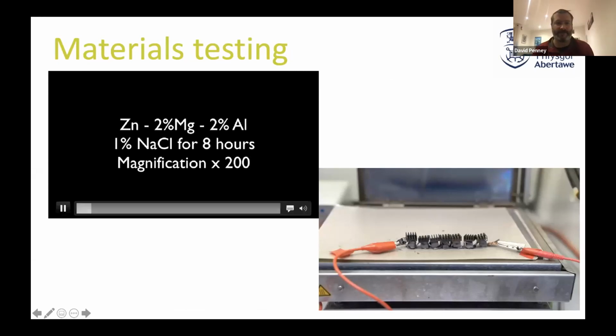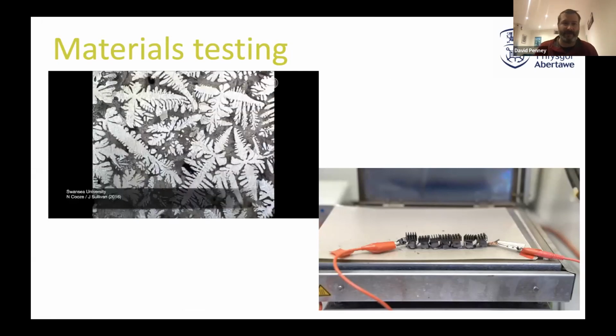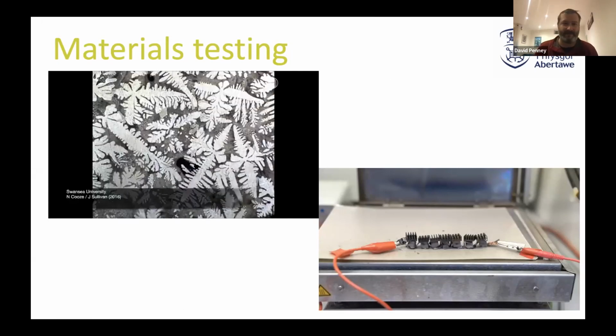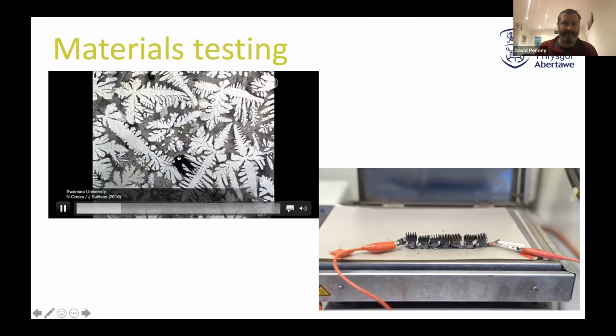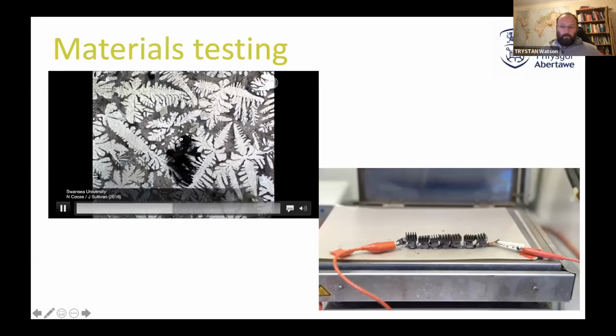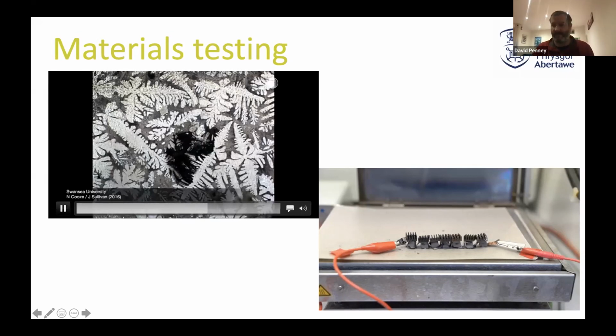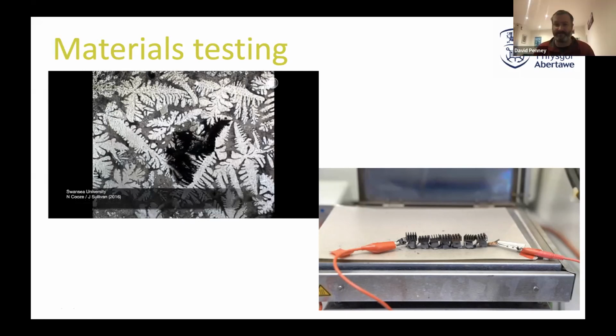And if we look here, we have a coating which has got magnesium and zinc in, and we're watching it corrode over time. So this black area here, which looks very sinister, travels through the steel here. These dendrites are about 20 microns across, and they're dendrites because they look like trees, which is the Greek for tree. And what you can see is the dark phase, this dark area, the corrosion is traveling in between these bright dendrites and causing some corrosion to attack that one particular phase.